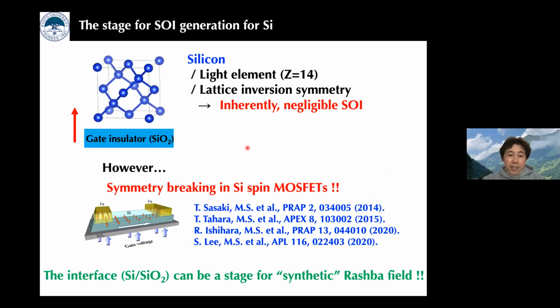So in the rest of the time, I briefly introduce our latest result on the tunable SOI in silicon. As you know, silicon is a very light element. The atomic number is only 14, and silicon has a lattice inversion symmetry. From these facts, silicon inherently has a negligibly small SOI. But this holds for bulk silicon. In practical devices, an interface usually exists, for instance, in a transistor the gate insulator exists. And when we look at this interface, the spatial inversion symmetry is broken along this direction.